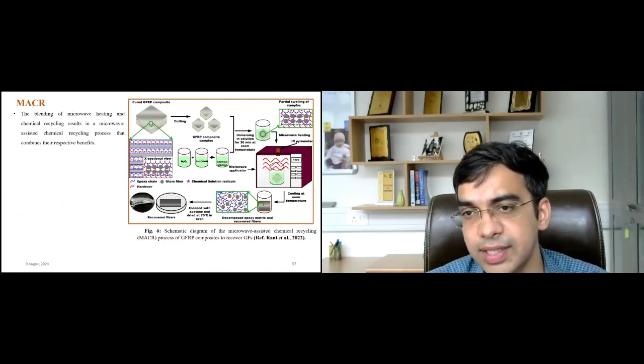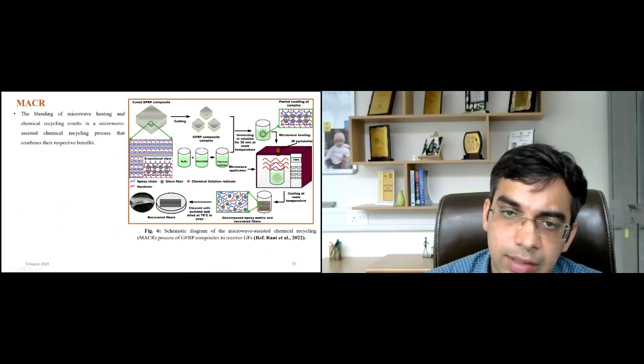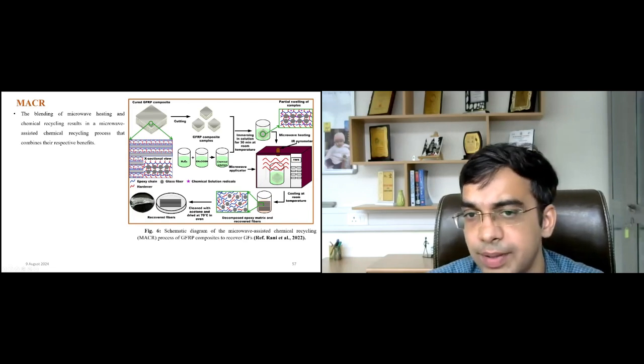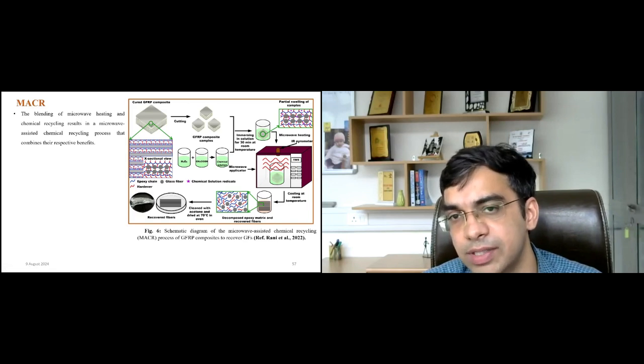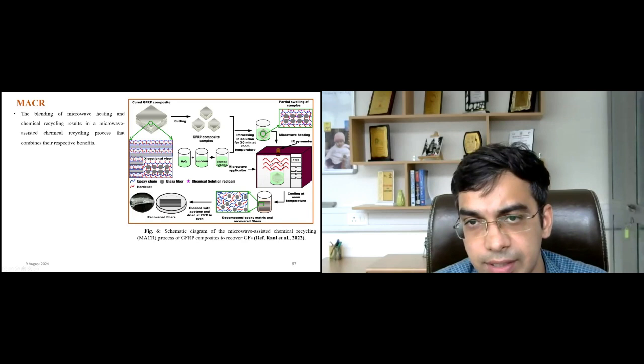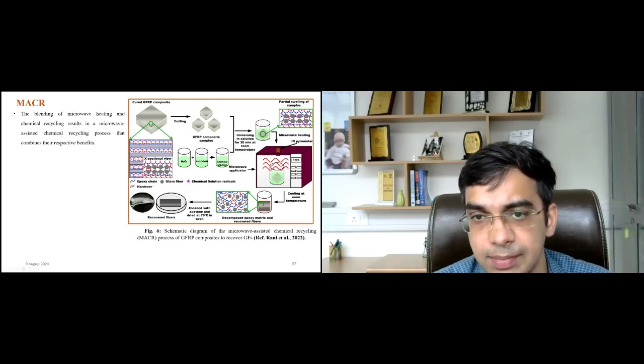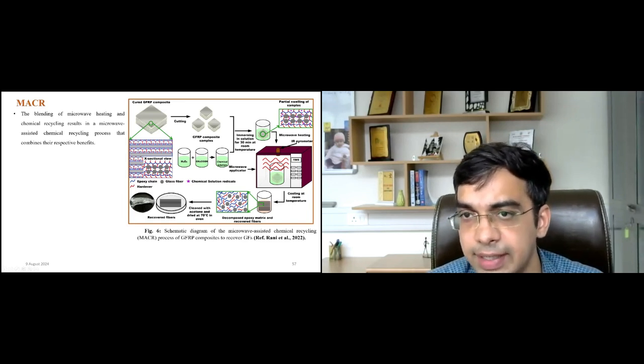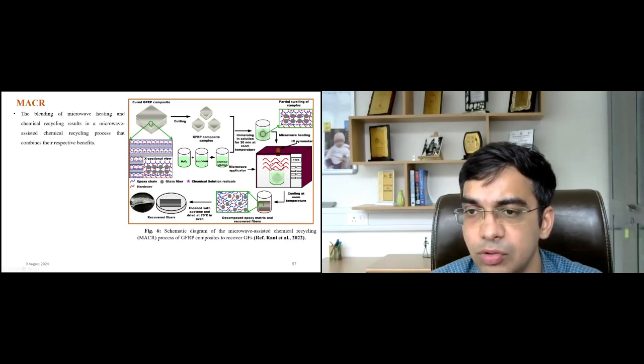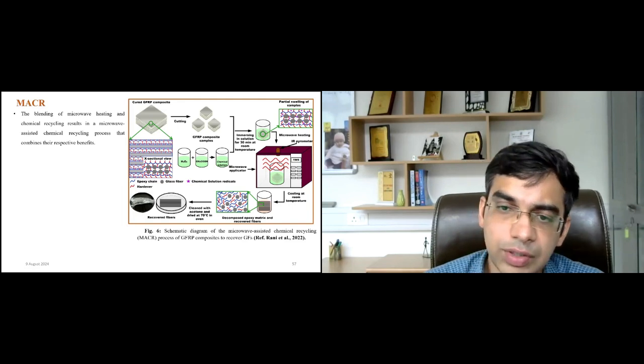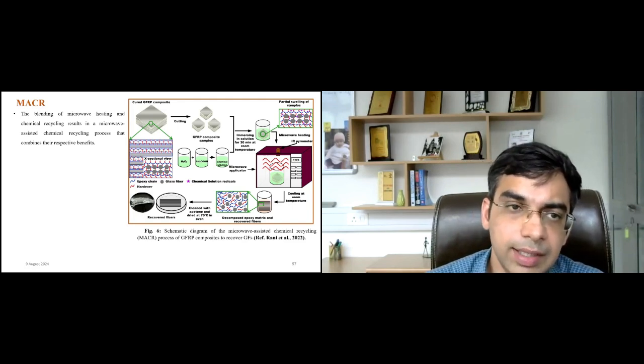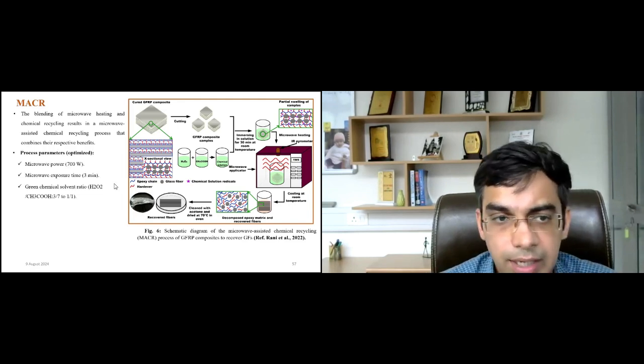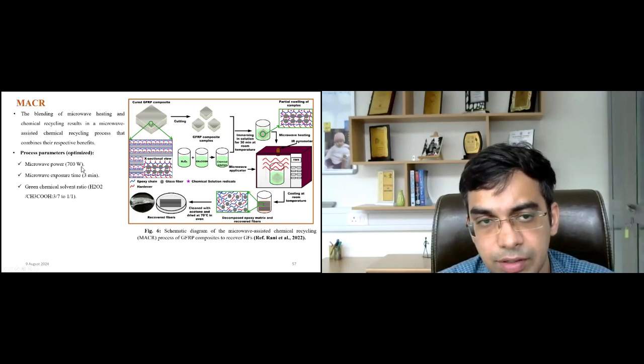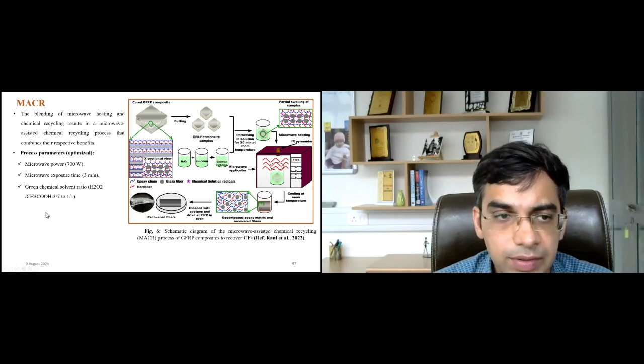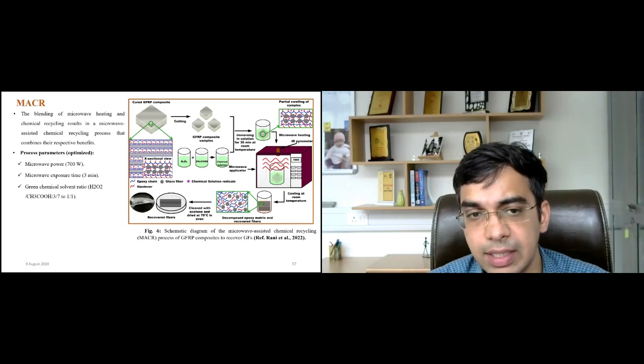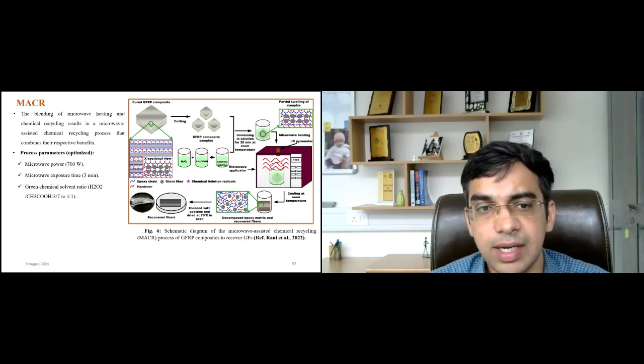In this process, again, we are utilizing microwave energy, but in this case, the chemicals which are used are derived from a green chemistry approach, which include hydrogen peroxide and acetic acid. What we observed is that we subjected the epoxy, glass fiber based composites, the same samples which we manufactured in the previous case, to this combination of chemicals, immersing them for 30 seconds at room temperature and then subjecting them to a domestic microwave for a few hundred seconds. We could dissolve the epoxy out and recover the fibers after cleaning with acetone. In this work, we used microwave power of 700 watt for recycling and an exposure time of 3 minutes, with this ratio of chemicals derived from the green chemistry approach, which is hydrogen peroxide and acetic acid.